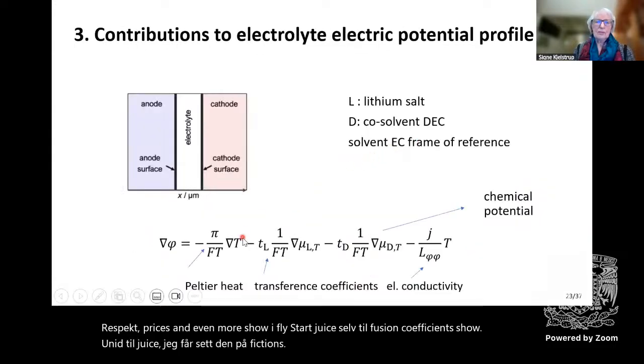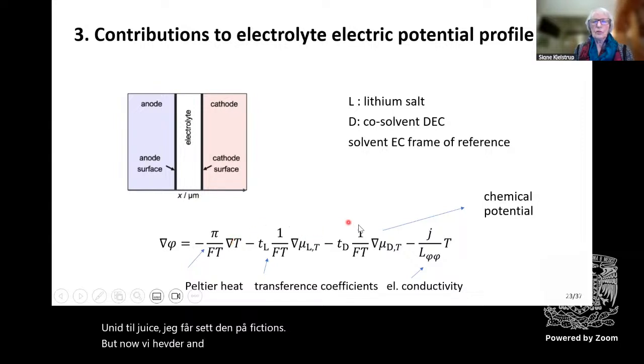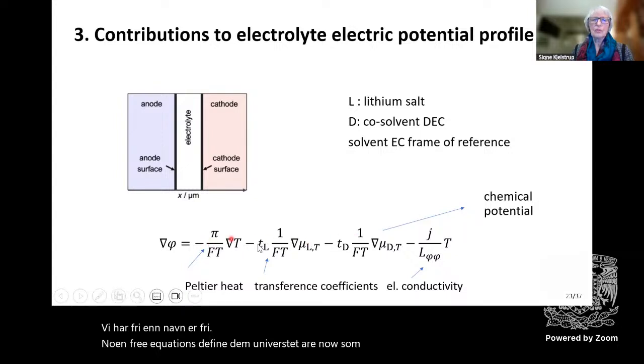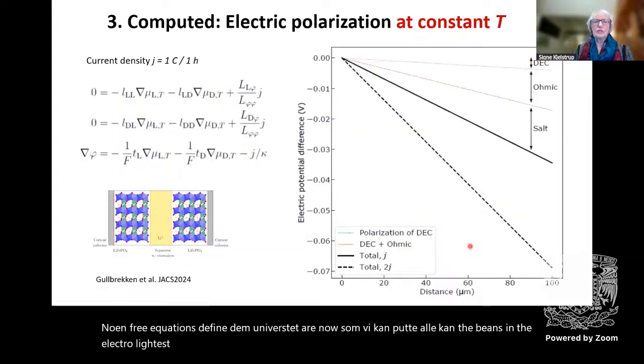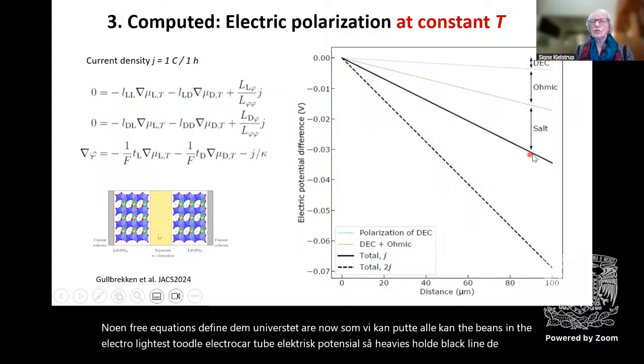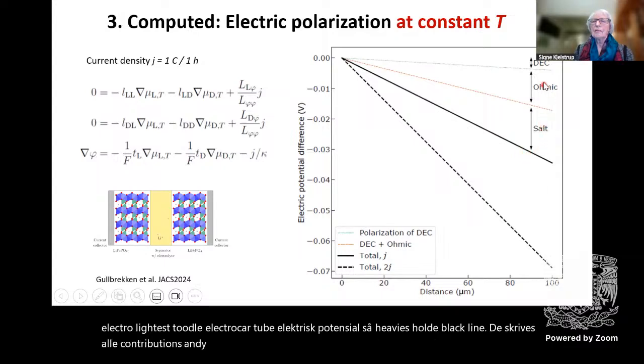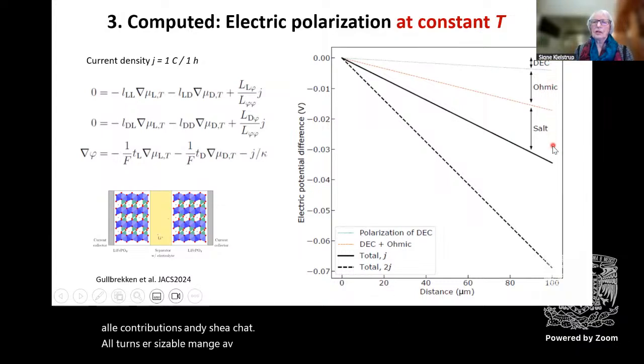But now we have them, and we can compute. We have 3 unknowns and 3 equations to find them, and the rest are known. So we can compute all the contributions in the electrolyte to the electric potential. So here, this whole black line describes all the contributions, and you see that all terms are sizable. None of them can be neglected.